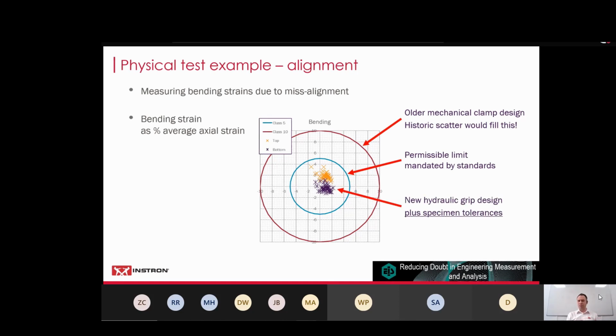Now, this data in particular I'm presenting here is some work we did. Once again, look! Here's some nice data. So apologies for the slight commercial bias there. There are other people who've done similar stuff. You'd get a really good grip design, and you can get your scatter really, really tight. So this is something like 38 different repeat measurements, and you can see that's really, really repeatable. And that's where, in modern times, we should all be trying to get to, because we're getting right down to the limits of what's physically available, and we're not introducing significant scatter to our results just by inadequate clamp design.